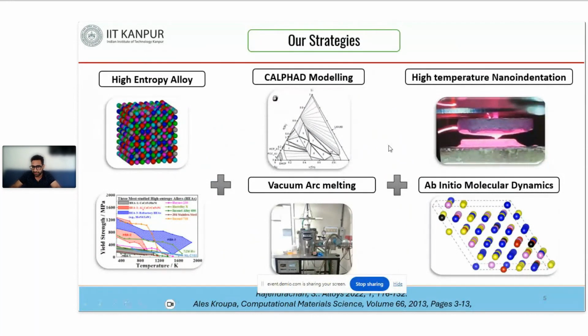To deal with the fabrication process, we have used the vacuum arc melting process, and to study the deformation behavior, we use high temperature nanoindentation testing, which is robust and also requires a very small amount of material. Since they are new materials, we are limited in the amount of material we have. And to understand the deformation behavior at the atomistic level, we have used ab initio molecular dynamics simulation, which gives accuracy and is also able to simulate a decent amount of atoms in the supercell.